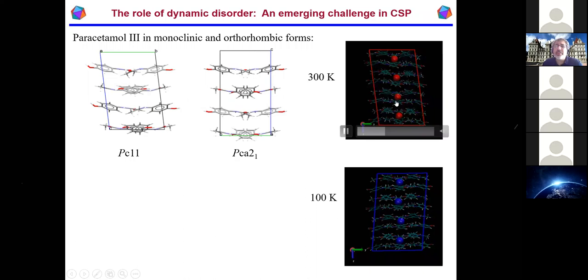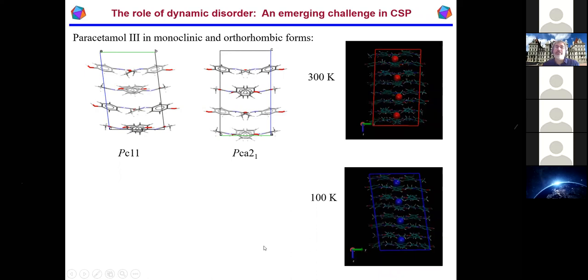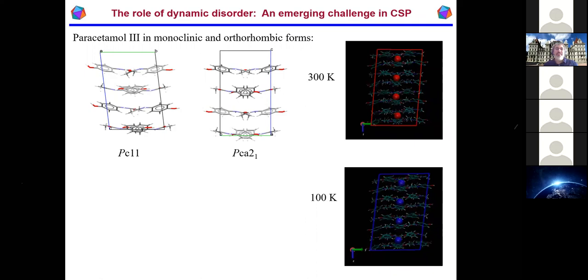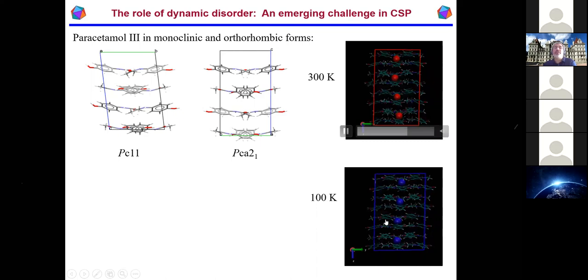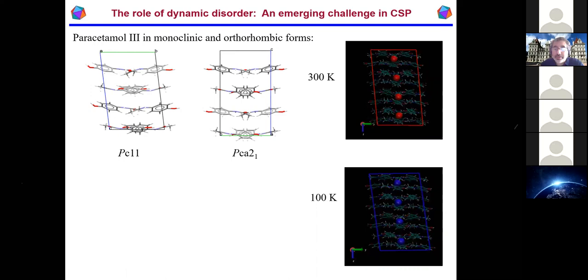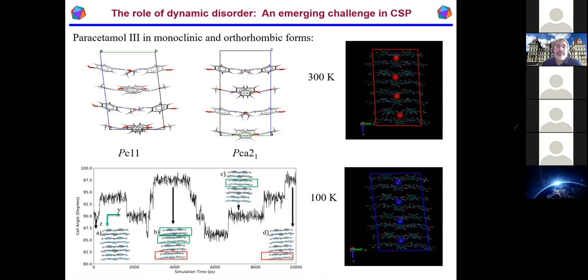Now I'm showing you an MD simulation at 300 Kelvin and also one at 100 Kelvin, all right, just to show you that the transition between the orthorhombic and the monoclinic phase is kind of a rare event. There's a large barrier there. At 300 Kelvin, it's easily crossed, but at 100 Kelvin, which is actually a relevant temperature, it's not. But what I want you to see in these movies, especially the 100 Kelvin one, is that the actual crystal structures themselves involve a certain degree of disorder.